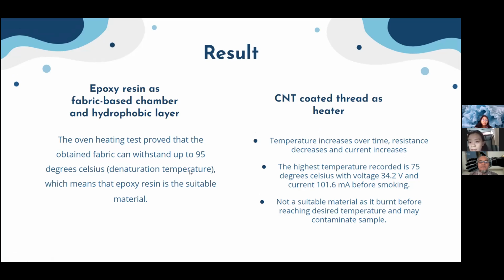As for the CNT coated thread as heater, as temperature increases over time, the resistance decreases and current increases. However, the highest temperature recorded that can be reached is only 75 degrees Celsius with voltage 34.2 volts and current 101.6 milliampere before it showed signs of burning and smoke. So we can conclude that it is not a suitable material for the heater as it burned before reaching the desired temperature and that they may contaminate the sample.